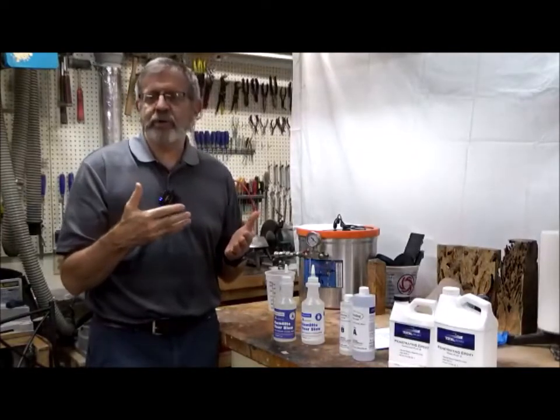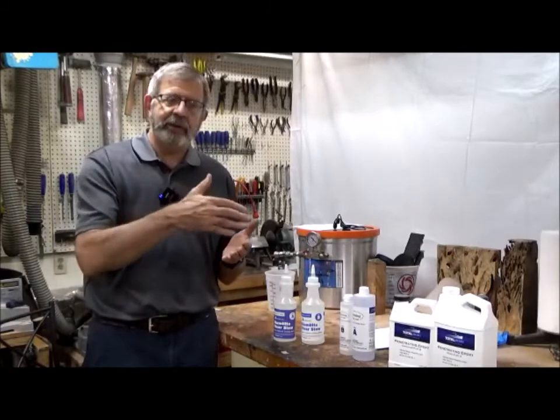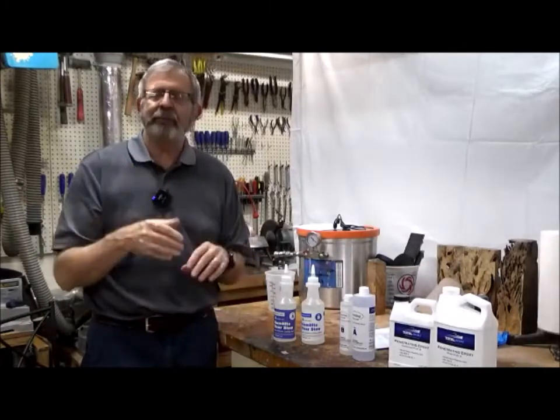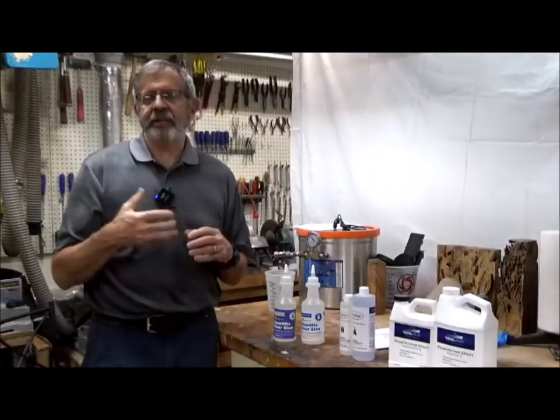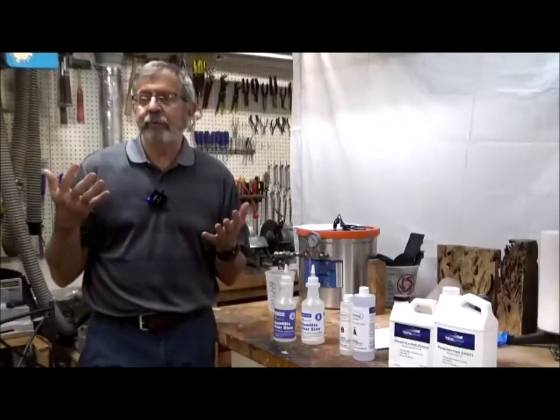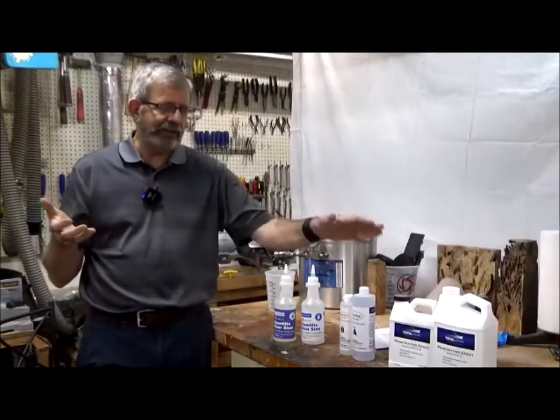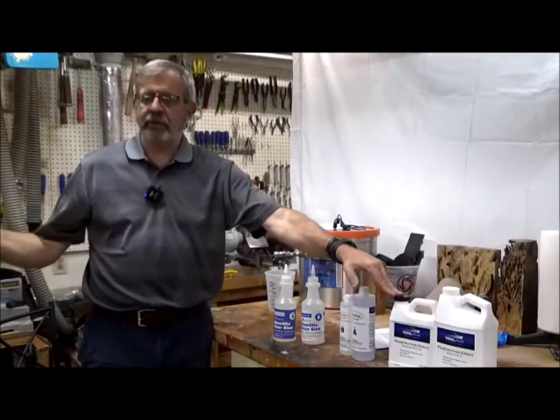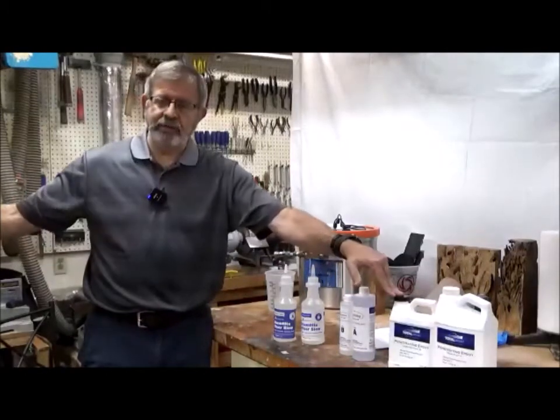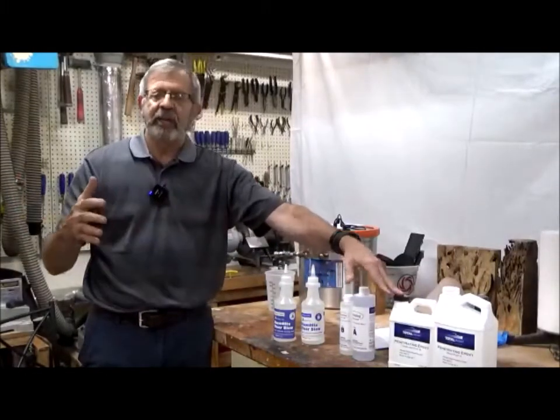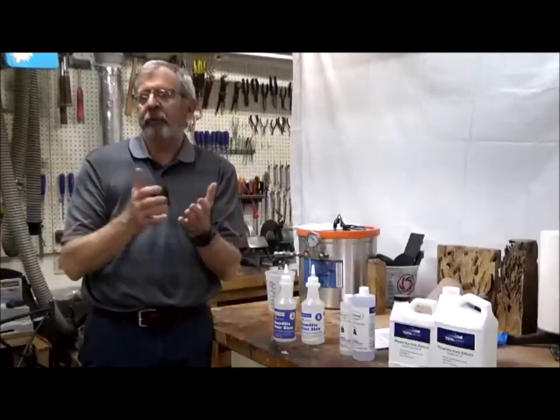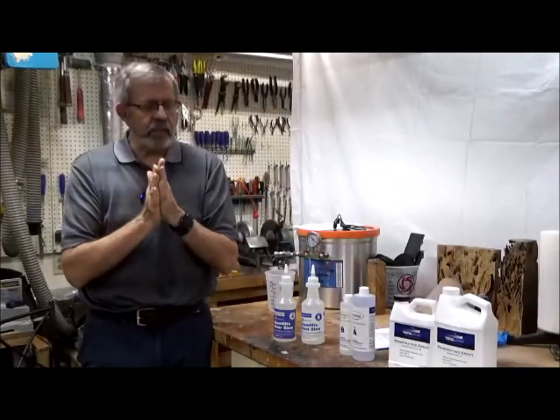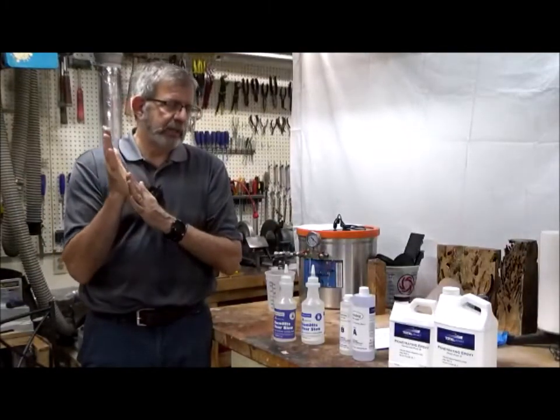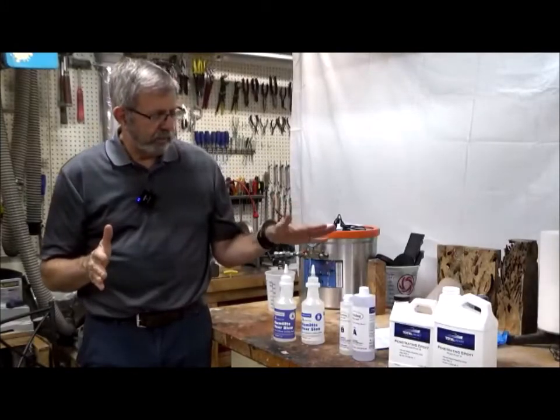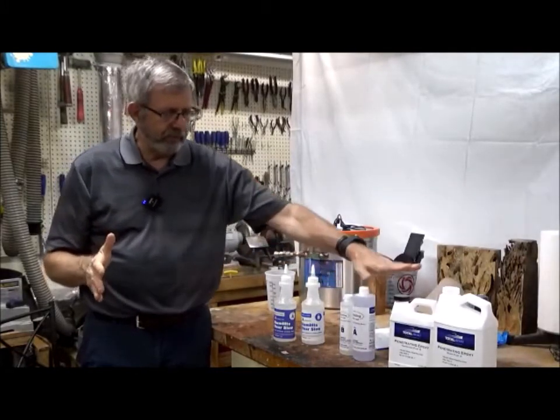you can use either a torch or a heat gun on your piece to bring the bubbles up to the surface. You see the guys that are casting these big river tables, that's what they're doing. They're using these really slow set epoxies, and they're using a torch or a heat gun over the entire surface multiple times in order to bring the bubbles to the surface. And that's the way to get rid of the bubbles. So these are the three.